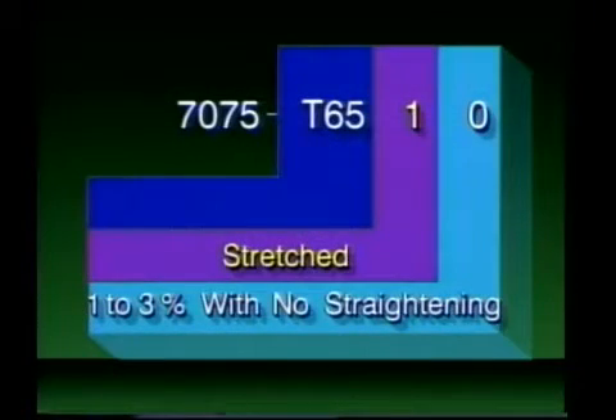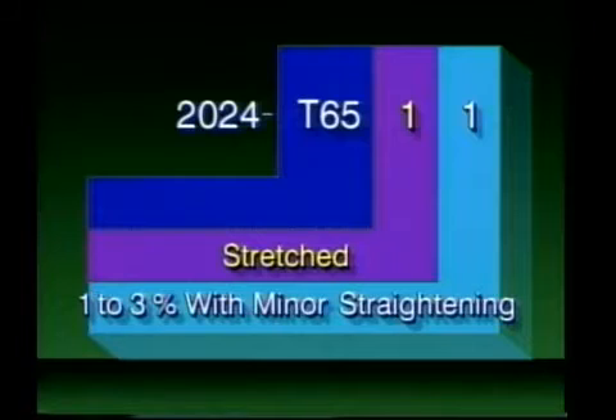For some product forms, when stretcher stress relieving, such as denoted by TX51, is applied, an additional descriptor digit is used to indicate the amount of the stretch. Examples include 7075 T6510, stretched 1 to 3% with no straightening allowed, and 2024 T6511, stretched 1 to 3% with minor straightening allowed. When using the stress relief nomenclature, the 5XX or 5XXX series of numbers is always positioned at the end of the respective temper it represents. For example, T73511, T4251, T652.